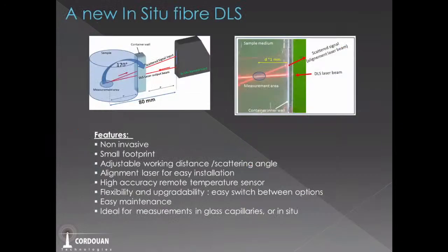So the idea is that you have the light coming in, and at 8 centimeters, we are gathering the light here, and we detect the light coming into the optical fibers. So the volume that we are measuring is a small volume. Imagine that we launch a laser into the input, and you put a laser on the output. You can see here that we are studying a volume which is around 400 microns in length and 100 microns in width. This is the volume that we are measuring.